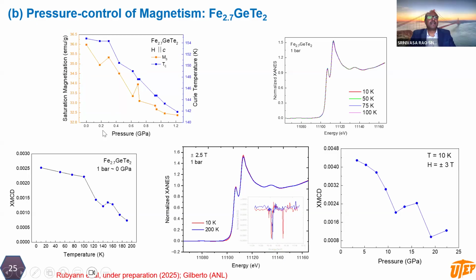In our lab, we did pressure-dependent magnetic measurements. As you can see, the magnetization starts decreasing, as well as the Curie temperature, up to about 1.2 gigapascal. And we went to Argonne National Lab and conducted XMCD measurements as a function of pressure. As you can see, up to about 23 gigapascal, the XMCD signal decreases in the ferromagnetic phase. So it means that the ferromagnetism did not increase as a function of increasing pressure in this compound, unlike the earlier compound where the Curie temperature increased with increasing pressure.